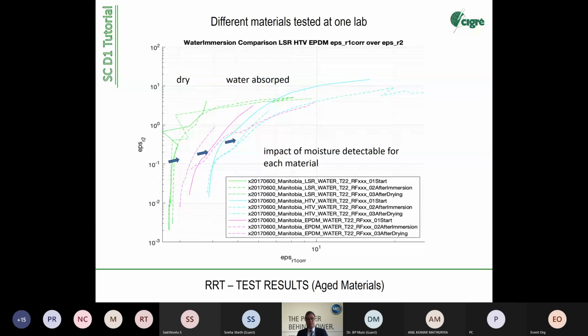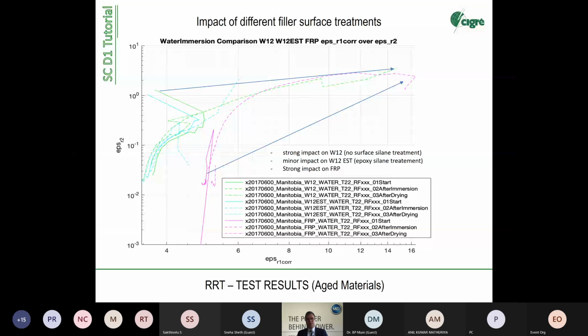Here we have studied different filler surface treatments. And here now I'm on the right way. Strong impact on W12, so no surface treatment. You see a big move from initial conditions to water immersed conditions. And you have a minor impact on the surface treated quartz filler in epoxy. So that's very clear, which means we can detect quality of microscopic interfaces. We can distinguish between good and bad materials.